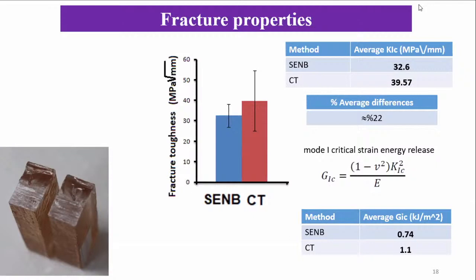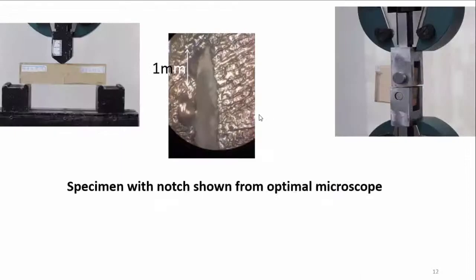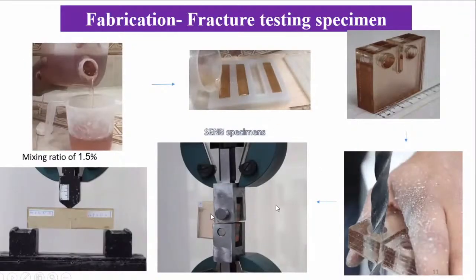Okay, I have a couple of questions that I can ask. We see that the discrepancy of the data is quite large for the CT specimen. But considering the average value, or let's say the median value, what do you think is the reason for the 22% lower values when you're testing with the SENB specimen? One of the ideas that we got, based on our fixture, is maybe the out-of-plane bending that we might end up with while applying this kind of load, similar to tensile testing, in the CT specimen. That might be one of the reasons. We noticed that we have a little bit of a kink in the fracture surface, so it's not as flat as expected.